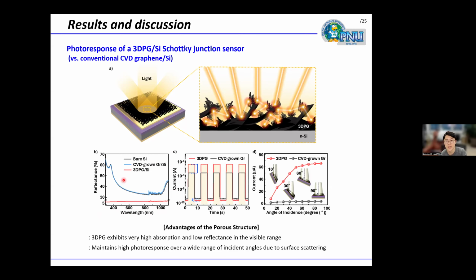It means that this device can effectively absorb the outer optical energy. In addition, due to the multiple scattering within the porous structure, incident light from various angles can be effectively absorbed in this Schottky junction device. As a result, the device shows a high detection efficiency over a wide range of incident angles.